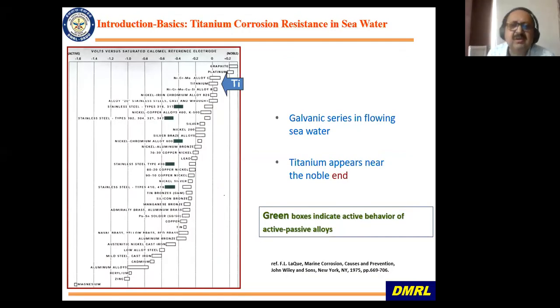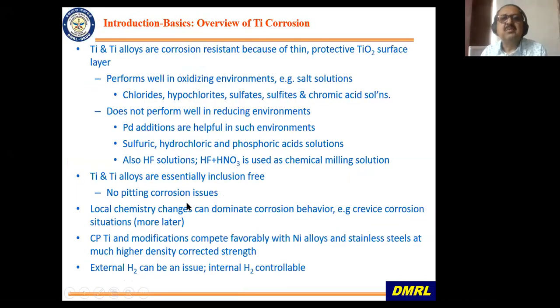Now, let me talk slightly about the corrosion resistance of titanium. Titanium, as you know, has very good corrosion resistance. Here, the galvanic series in flowing seawater is shown, and you can see titanium is towards the top end, so it has very good corrosion resistance against seawater and also many other chemicals. Titanium has very good corrosion resistance because it has a very thin protective layer of TiO2 on the surface. It forms, but mind you, this is not as impervious as in aluminium. So it does oxidize, but still it serves a lot of purposes and it protects titanium.